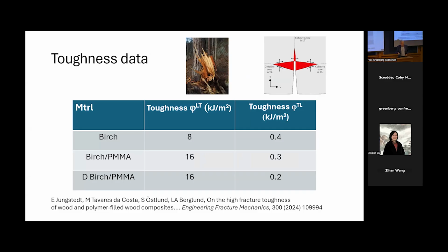So it appears, if you look at the tree stem that is broken, that one of the reasons we see this toughness is that there is such an enormous large volume of the wood material that is fracturing. We have cracks all over the place. And it's sort of a paradox that one reason is that the material is really weak in one of the directions, and that is causing these complex energy absorption processes.